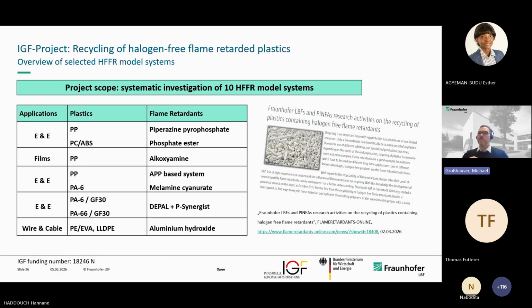You see them on the bottom here, or the left bottom side. And also it was quite well accepted from media. So we did some publications there because of some interest all over the industry. Because the basic investigation was, if we have flame retardant plastics and we do a simulation in this field, what's happening when they get recycled? What's happening if they age and you want to reuse the material afterwards? And we started to do that in a simulation way. So we know what we put in there from an energy side and from a processing side.